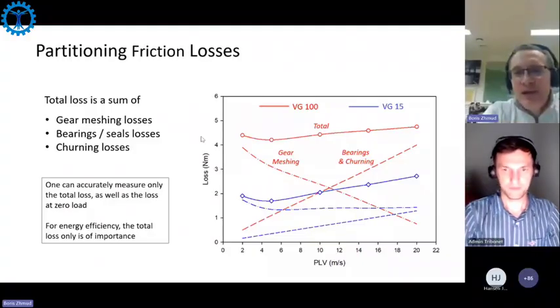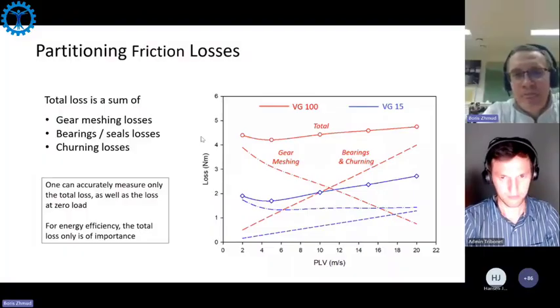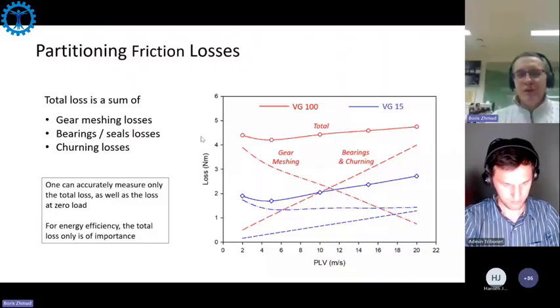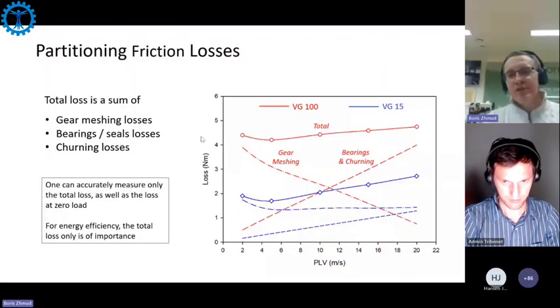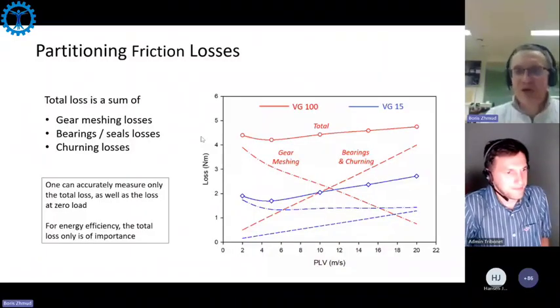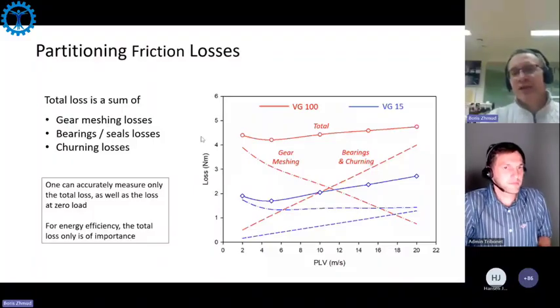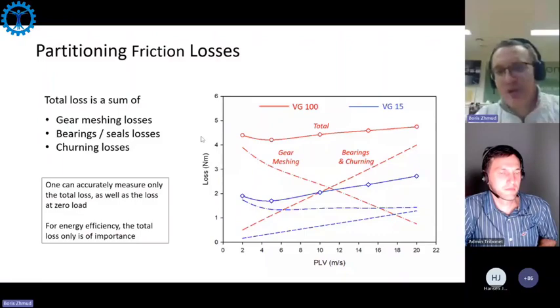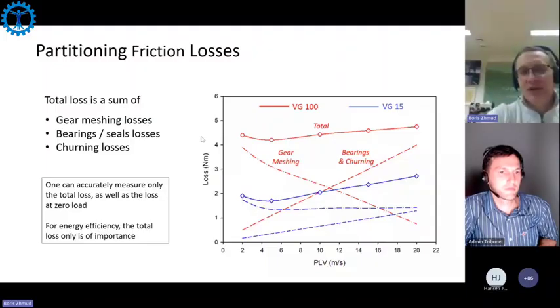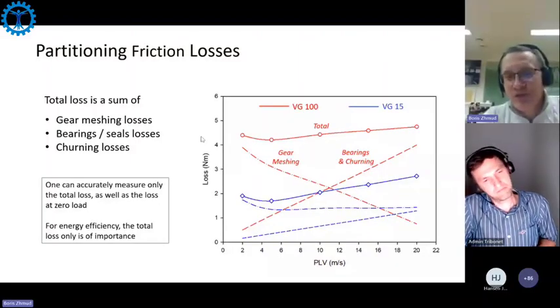Total is basically the uppermost curve, and then you can split it into bearing and churning losses, which you actually measure when you run your rig without any loading. And of course, it's based on the assumption that bearing friction doesn't depend on loading, which is not true, but it's the best approximation you can make. So you basically derive bearing and churning losses by running the rig without loading. Then you deduce bearing and churning losses from total losses, and the difference between total and bearing and churning is actually gear meshing losses. And you see that gear meshing losses are going down with increasing pitch line velocity.